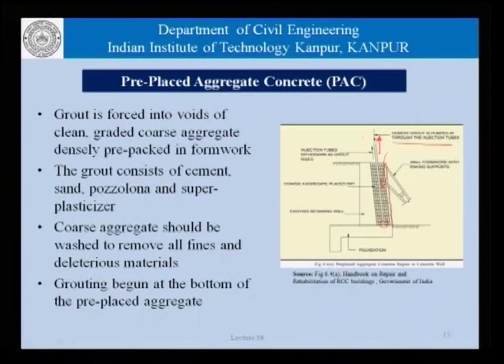So, grout is forced into voids of clean graded coarse aggregate densely pre-packed in formwork. It consists of cement, sand, pozzolana and superplasticizers. Coarse aggregate should be washed to remove all fines and deleterious materials, and grouting begins at the bottom of pre-placed aggregate. Obviously, we cannot start the placing of grout at the top and hope that the grout will simply flow down. It is better to start from the bottom and then go up gradually.